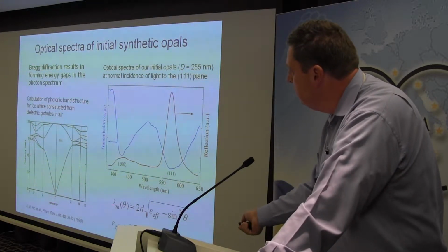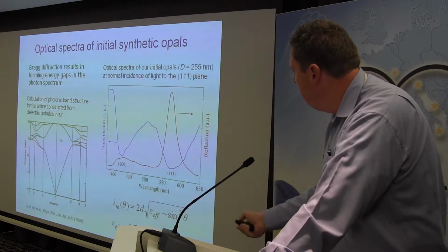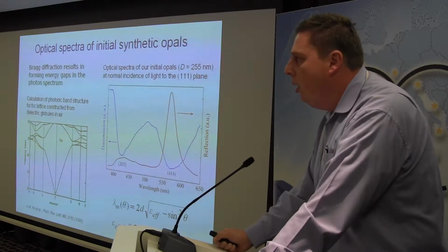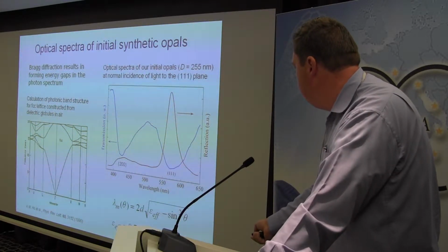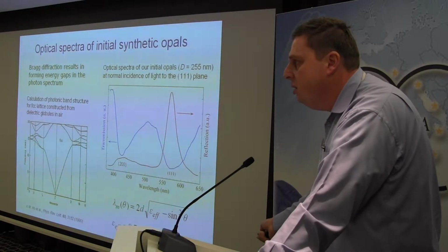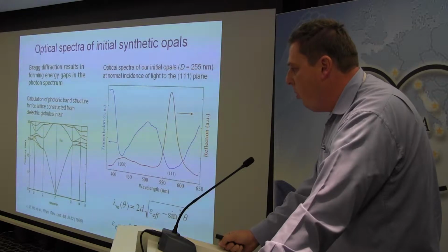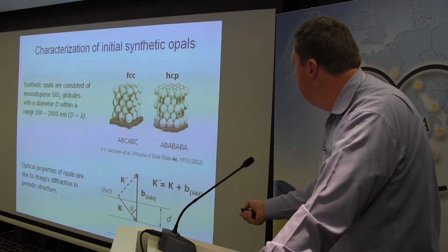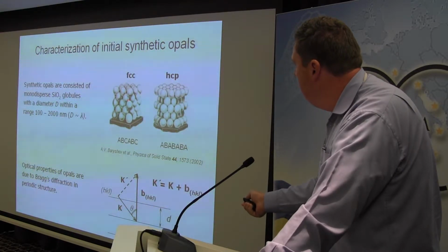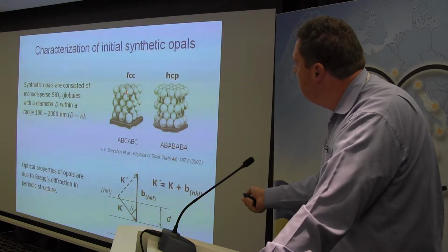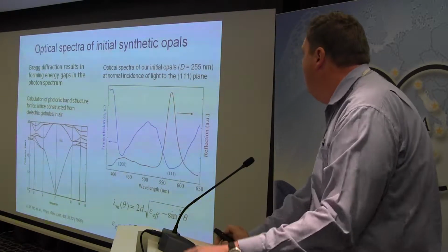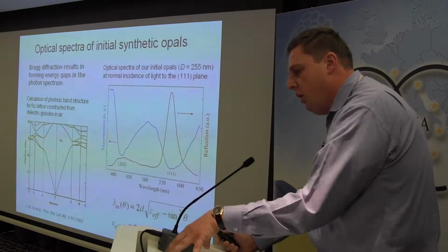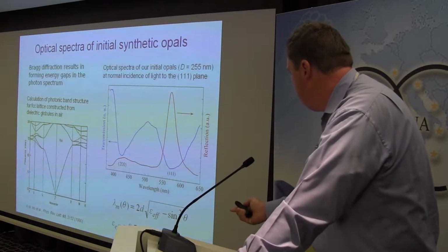The reflection peak or non-transmission peak is determined by the Bragg diffraction law, where epsilon effective is the effective dielectric constant, which is determined by the dielectric constant of silicon dioxide and other components which can be embedded into the opal structure. Synthetic opal consists of a regular structure of cavities or channels, and this porous structure may be filled with the compound that you want to use.